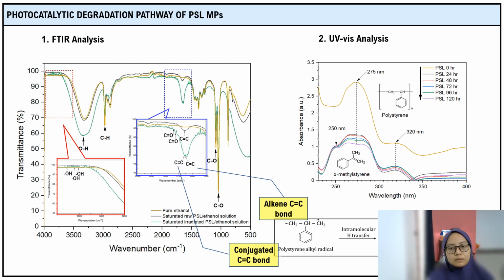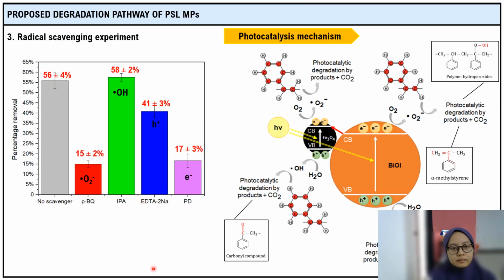This is supported by the UV-vis analysis, in which a new peak was observed at a wavelength of 250 nanometers, which indicates the presence of alpha methylstyrene. The radical scavenging experiment was performed to identify the main active species in degrading the polystyrene microplastics. It can be observed that in the absence of scavengers, the polystyrene microplastics can be degraded up to 56%.